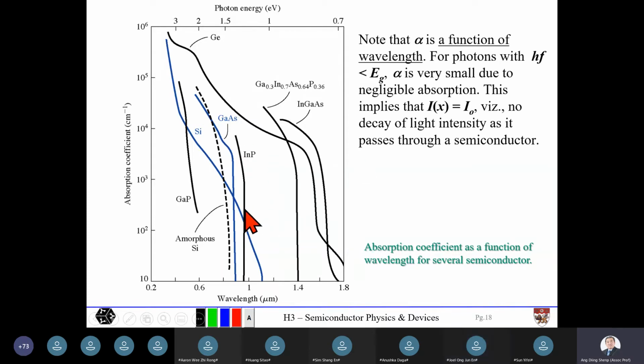beyond the cutoff wavelength, there is no absorption. Imagine you have doped silicon. As you mentioned, there are donor and acceptor levels. That reduces the photon energy needed for electron hole pair generation slightly. So in doped semiconductors, this effect is shown as a small tail. For example, in this case, there's a tail here. This tail could be related to some of the defects present inside this semiconductor. There's a tail near the cutoff wavelength.